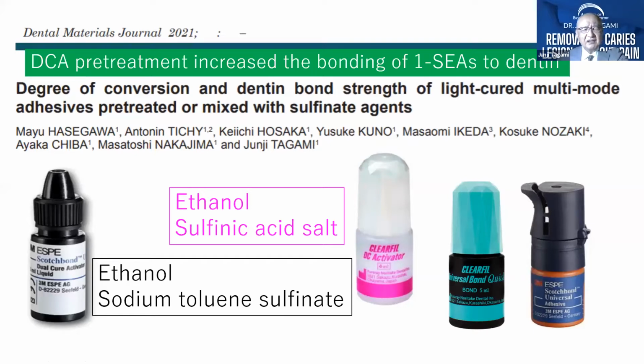In general, with this kind of one-step self-etching adhesive, the polymerization is not so easy because the solution itself is in an acidic condition. That's why sometimes the polymerization is not so easy. That's why we could improve the conversion of those materials with this kind of DC dual cure activator primer.